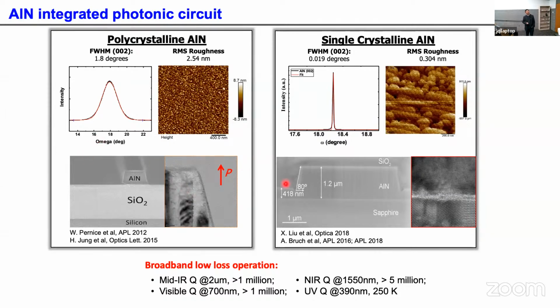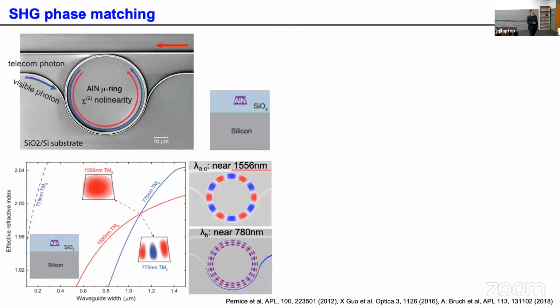The other type of material is single crystalline aluminum nitride, done by MOCVD growth on sapphire here. You can see the X-ray rocking curve is very narrow, there are no domains, and the roughness is much smaller, typical of silicon roughness. You can polish even further to get a smoother surface. With this material, you can get a pretty high Q: in the telecom band, more than 5 million, and down to UV, we can get about 250K Q. So it's very broadband thanks to its large band gap.